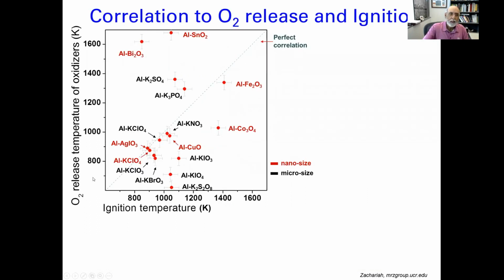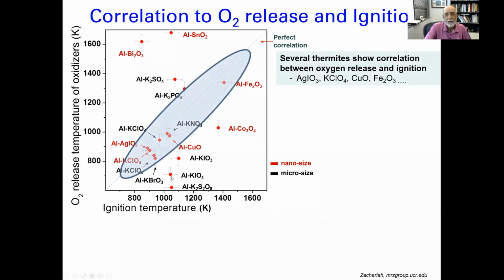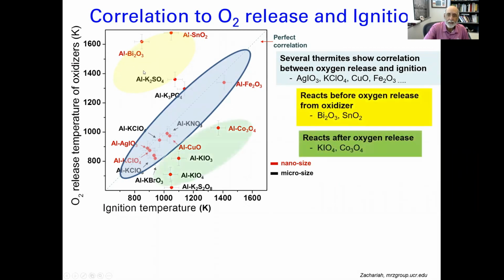So this is now the release temperature of oxygen that we measure with our mass spectrometer. And then we mix this with aluminum and measure the ignition temperature. Now, if there was a correspondence for when oxygen comes out and when the system ignites, everything should follow dotted along the diagonal. But clearly, it does not. Some of them follow the line. Okay, there's a correspondence between when oxygen comes out in the gas phase and when it ignites. But then there are examples where the system ignites before oxygen ever comes out. The oxygen release occurs late. And there are examples where oxygen release occurs early and the system ignites late.